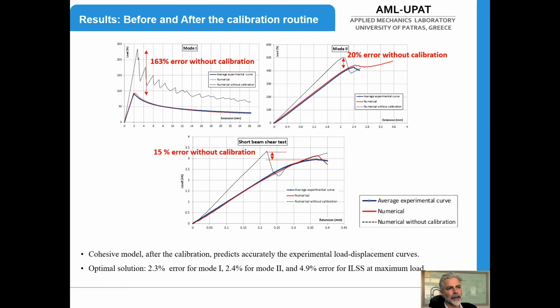As you may see, the optimized material parameters give results extremely close to the experimental data, while there is a significant difference between the experimental data and the simulated experiment in case we have used the reference material properties. It is important to notice that the difference in the top load is close to 163%.